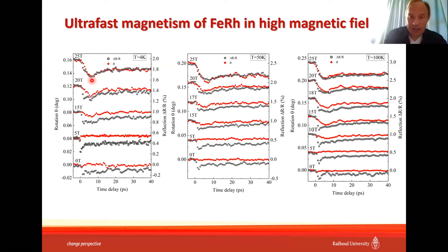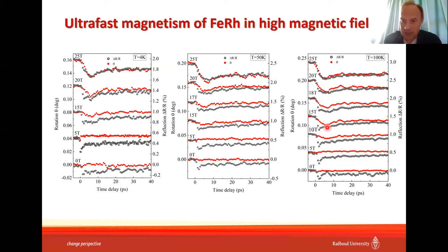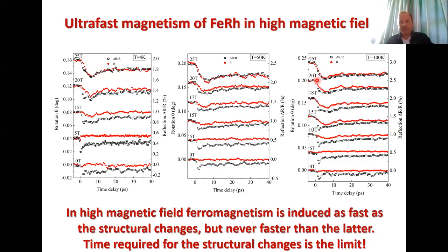So here again, we can go to higher temperatures. We see phase transition. We can trigger phase transition at already 20 Tesla. Again, it goes in step. Structural changes go in step with magnetic changes. And as we go to higher temperature, again, magnetic changes become faster and faster, never faster than the structural changes. So basically, at high magnetic field, ferromagnetism is induced as fast as the structural changes, but never faster than the latter. So the time required for the structural changes is the limit.